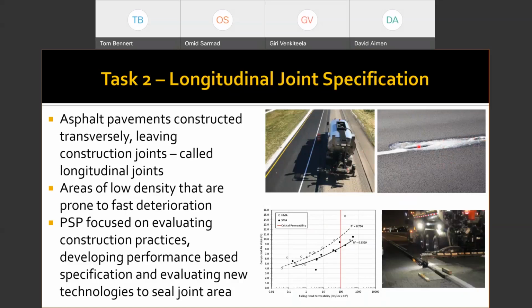Now, the problem with this is that during these sorts of cycles, you really start to weaken that joint. And then you start to actually see it fall apart during these freeze-thaw cycles, on top of any sort of moisture damage. And what you end up having is almost having to rehabilitate a pavement, not due to premature failure of the material, but due to the construction practice itself.